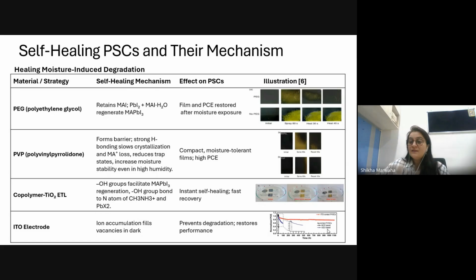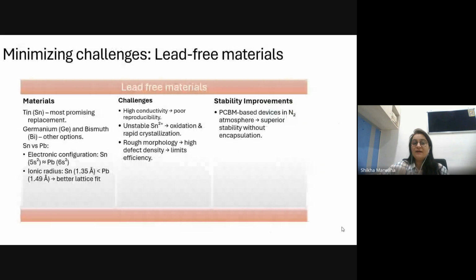So we can see that if we have a normal silver coated material, the normalized power conversion efficiency is decreasing. But if we have ITO as one of my electrodes, we can see that it is still constant. So yes, it is one of the materials or self-healing materials that can be used.